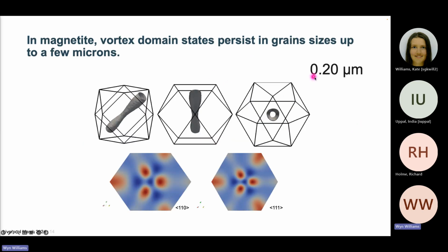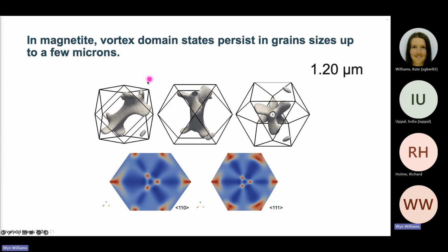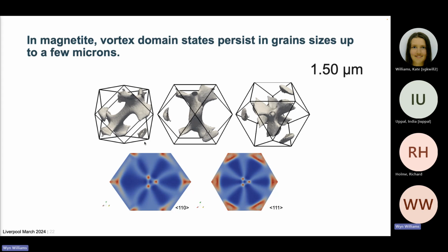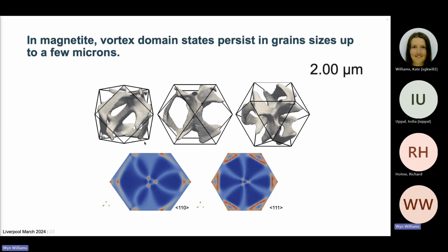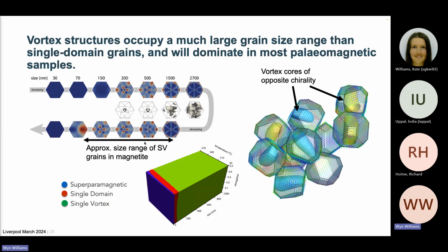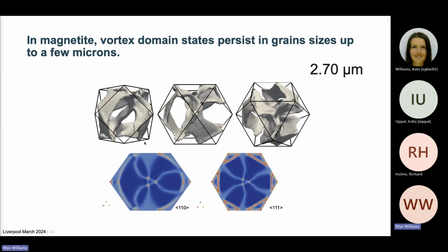So this is a 200 nanometer grain, already with a well-defined domain structure. And as we go up in grain size, you can see the development of these more linear structures at the outside of the vortex core. I'm going to go through this really quickly because it's not essential to the thread of the talk. But as you go up to 1.5 microns, 2 microns, and 2.7 microns, which we would say is at the boundary of the transition, in a roughly equidimensional grain, between what we normally think of as a PSD grain and a multi-domain grain.